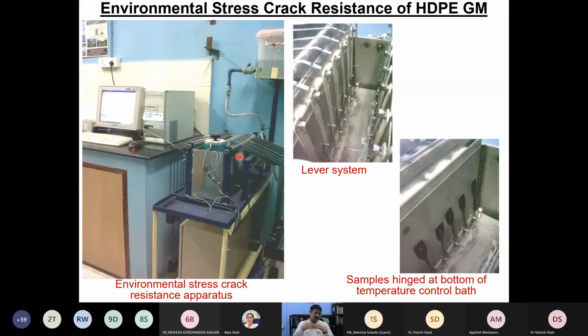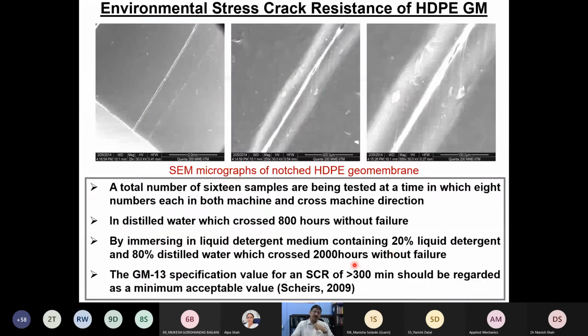Further, we also tried to see how the crystallinity of the polymer changes once exposed to photodegradation, and whether the change in crystallinity is reflected in the stress crack resistance. There is an apparatus called the environmental stress crack resistance apparatus, which we fabricated at IIT Madras. It's a very simple test using a dog bone sample. These dog bone samples are subjected to a certain amount of loading using a lever system. Before loading, we purposefully make a small, tiny cut on the polymer. Then we subject it to a certain tensile load, and immerse the entire thing in a detergent solution.